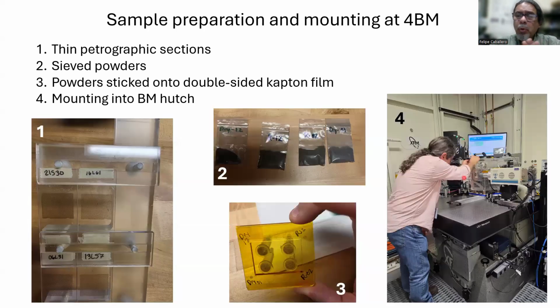Okay, so we took these two samples and the other samples indicated in the previous map. And here we can observe how the samples were prepared to be measured in the synchrotron in Brookhaven. These thin layers are petrographic sections of the powders. They were fixed in resin and ground down to 30 microns. So the sections are very thin, and the powder is very sparse.